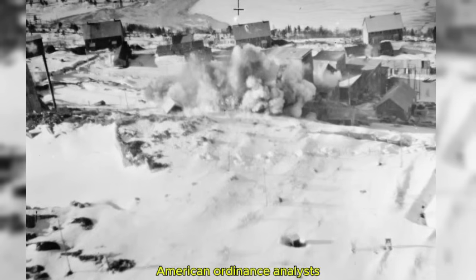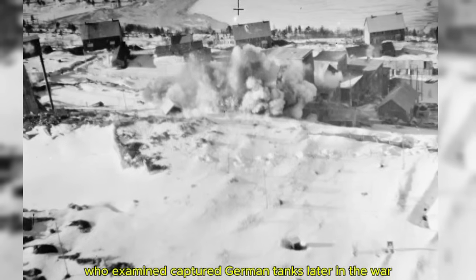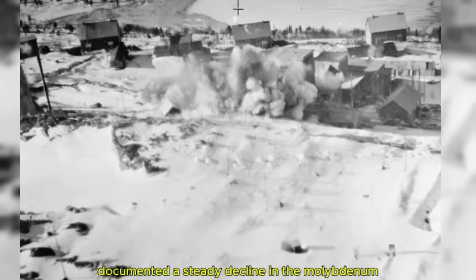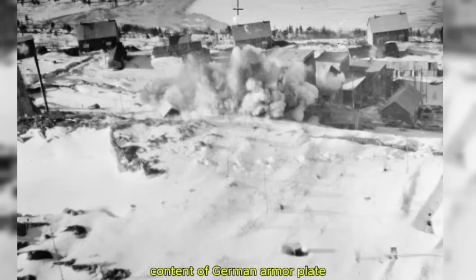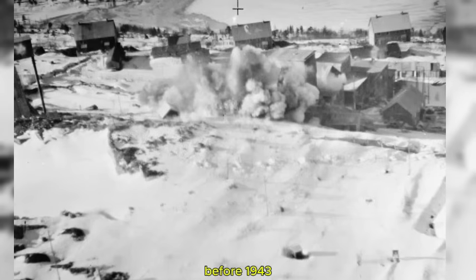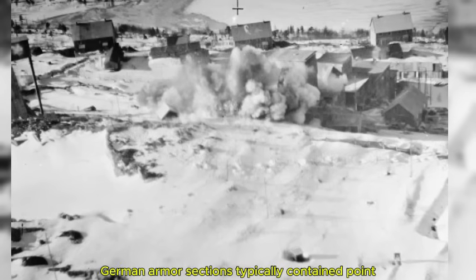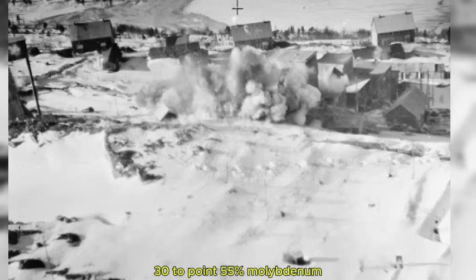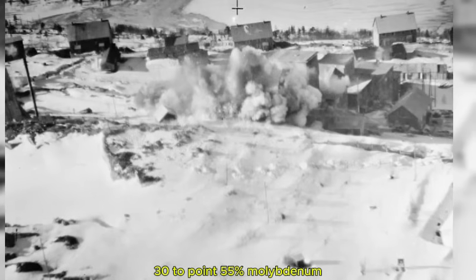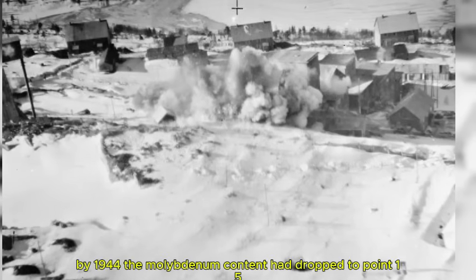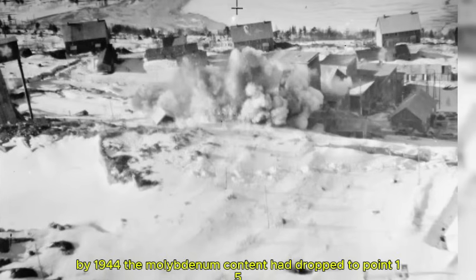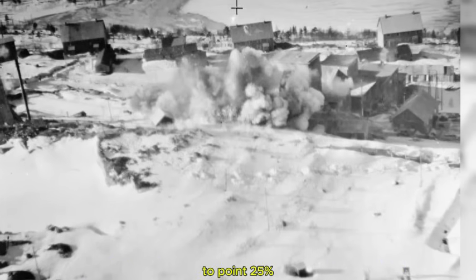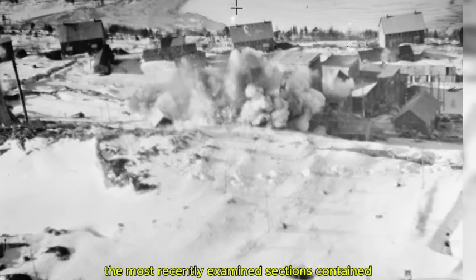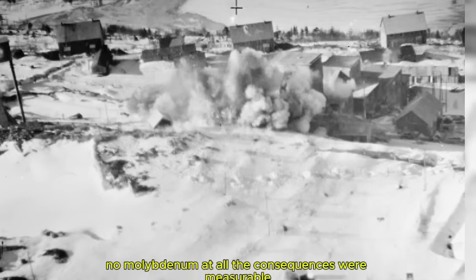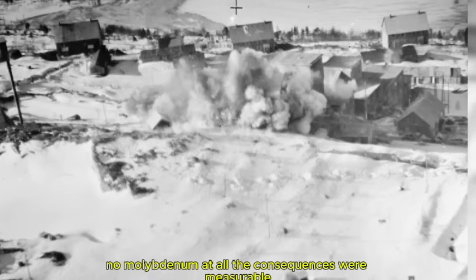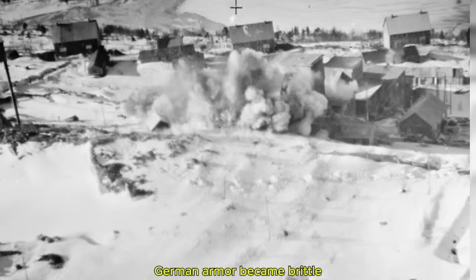American ordnance analysts who examined captured German tanks later in the war documented a steady decline in the molybdenum content of German armor plate. Before 1943, German armor sections typically contained 0.30 to 0.55% molybdenum. By 1944, the molybdenum content had dropped to 0.15 to 0.25%. The most recently examined sections contained no molybdenum at all. The consequences were measurable. German armor became brittle.